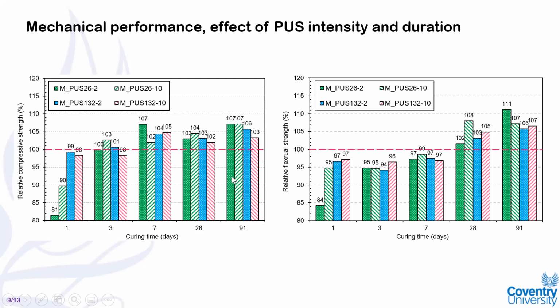But when the age of hydration goes up to 91 days, you can see the positive effect of sonication, specifically at 26 kilohertz, which is the higher intensity than 132, on improving the compressive strength of mortars, both compressive and flexural strength. You can see the better performance of higher intensity, the green bars, both in compressive strength and flexural strength. And you can see the positive effect of longer exposure of sonication, shown by the hatching bars, both green and the pink one, which is related to the degassing or deaeration effect of sonication.